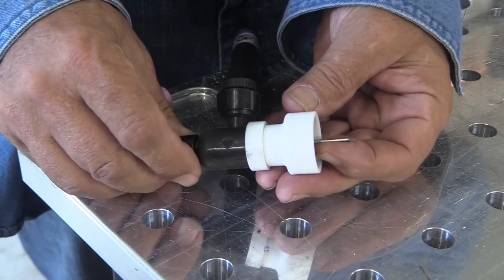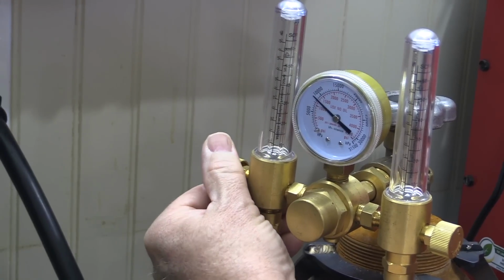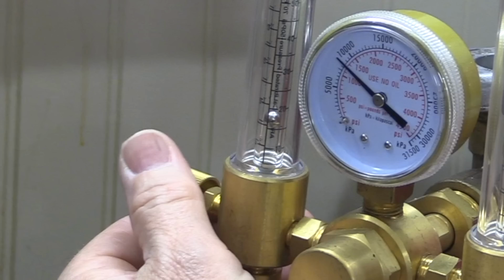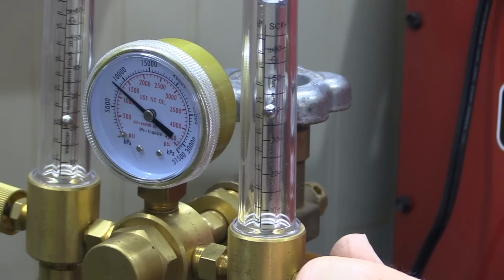I'm going to be welding this practice piece inside a fixture that purges, so I'm going to set my purge to start with to about 15 CFH. Hope that's enough. Torch gas will be set at 35 to 40.